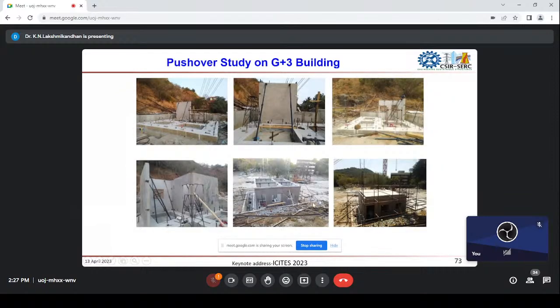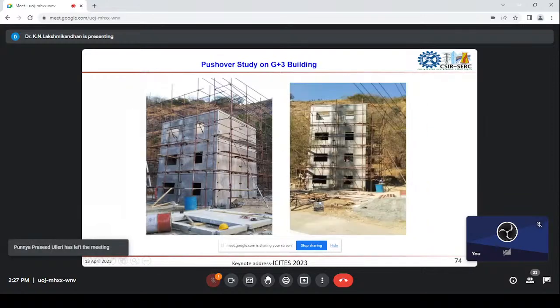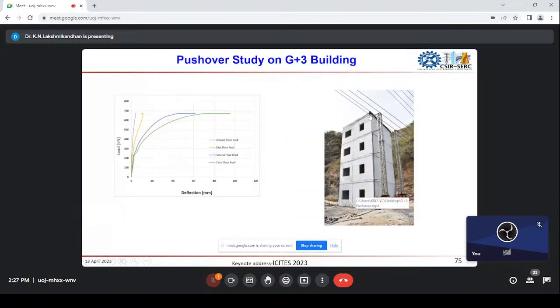And as we extended this technology for developing a G+3 building, it's a typical G+3 building assembled, and we tested it for the lateral load. We are using ropes to pull from the top, and we found that the structure we are developing with a lightweight roof and wall panels is capable of integrating together and carrying the load, whatever the zone 5 recommendations are. It satisfies the load conditions well below the requirement for the zone.